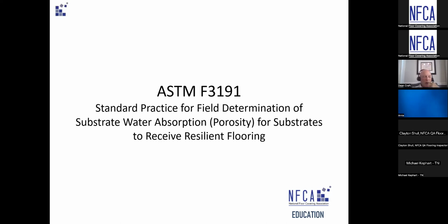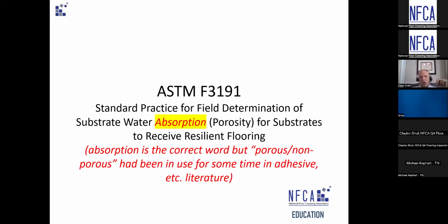And I don't want to be too gloom and doom here, but at point of installation, this is one of the most important, quickest, and easiest determinations that an installer can do. And as I said, even though it says absorption because it's the right word, we kept porosity in there because so much of the flooring manufacturers' literature said suitable for porous or non-porous, or open time and spread rate is dependent on site conditions and substrate porosity.